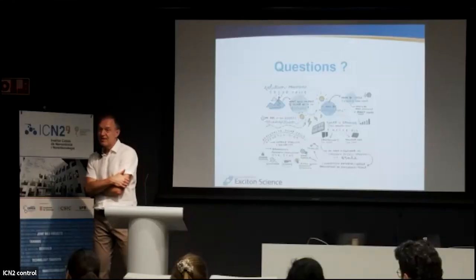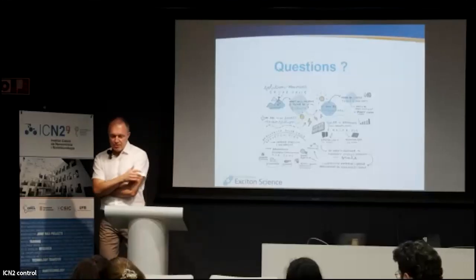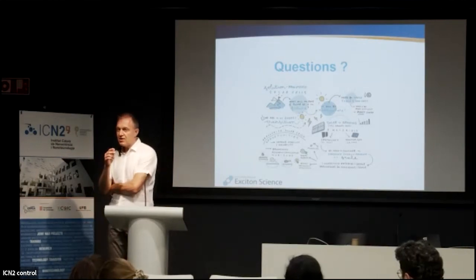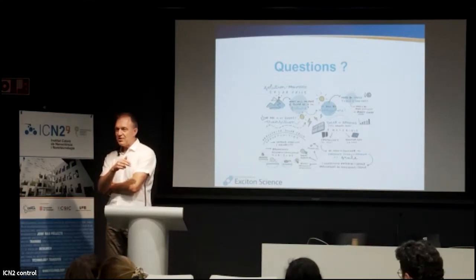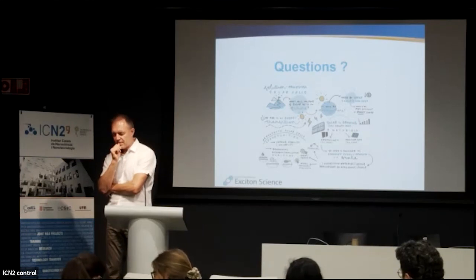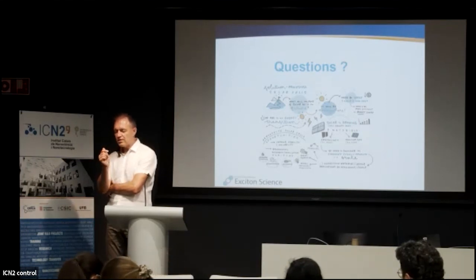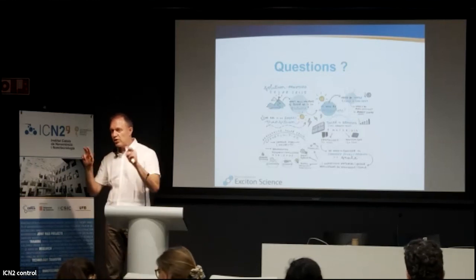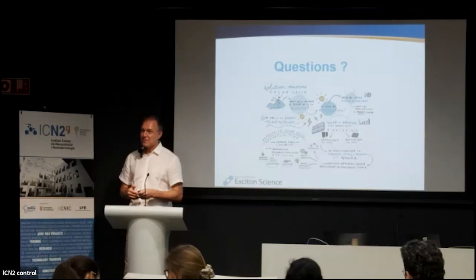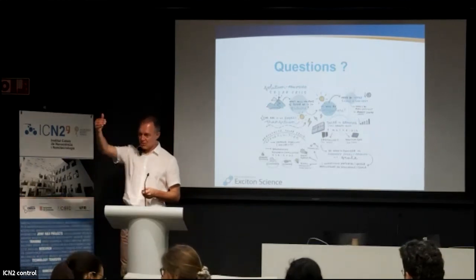About this phase segregation that you saw at low light intensity, that's low. It's still 10 watts per square centimeter. But how can we relate that to the applications of this halide perovskite for indoor lighting? We have to be a bit careful what we call low and high, because low is already very high. If you think of AM 1.5, that is 0.1 watts per square centimeter. What I call low here is 10, so we're already quite high above.